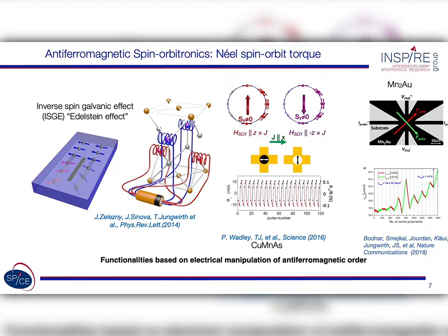Now, instead of reorienting with a Néel parameter torque, you are decomposing the system from large domains to micro domains, almost at the atomistic scale. And that seems to generate a current-induced switching, but switching in terms of switching the resistance of the system, that has some memory effects as well. But that is a unipolar effect that came from these studies.